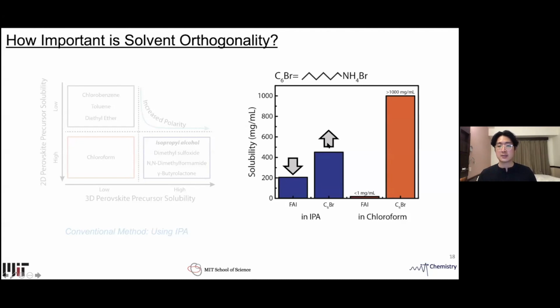And we in fact see that in the case of chloroform, where the difference is basically night and day. FAI is essentially insoluble in chloroform, whereas C6Br solubility exceeds a gram per mil. So this unique combination of using chloroform with C6Br provides the ideal discrepancy in solubility for post-processing.